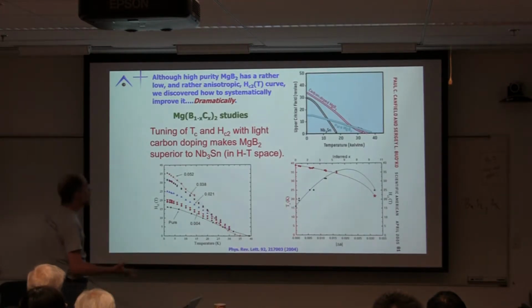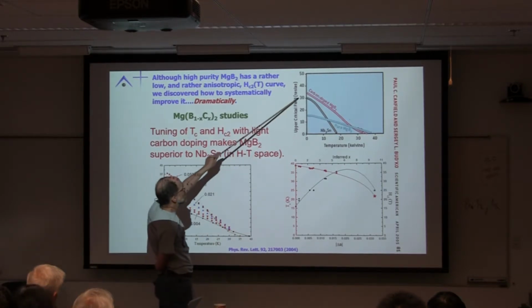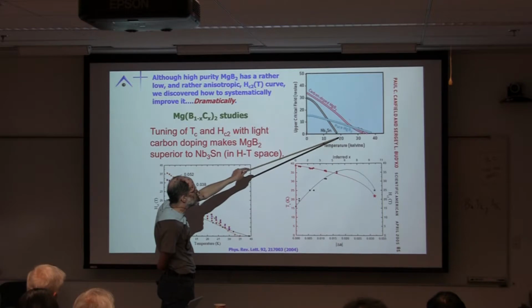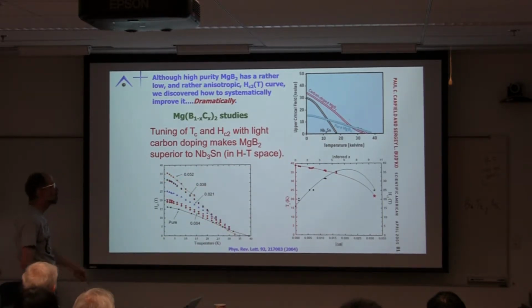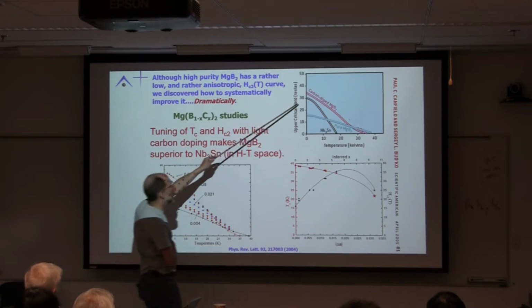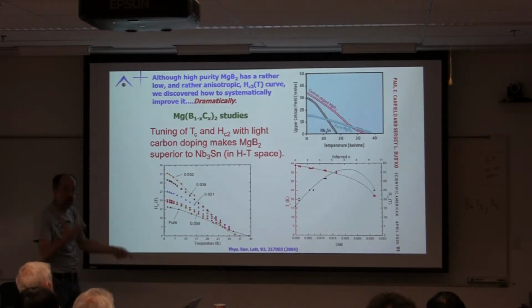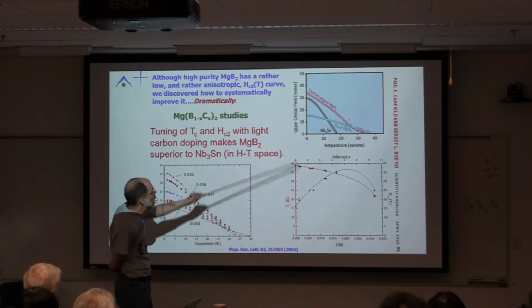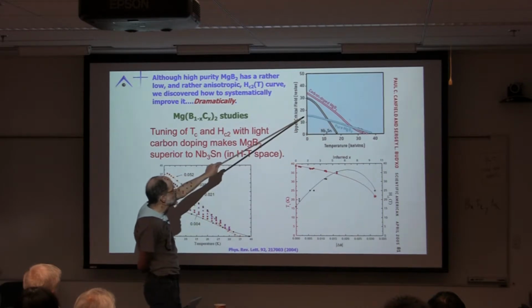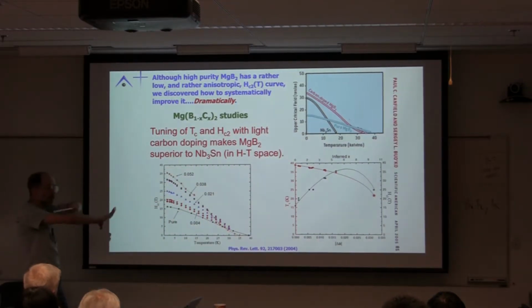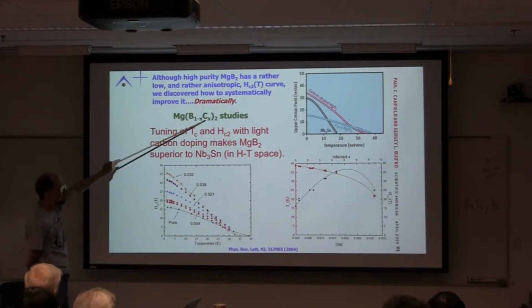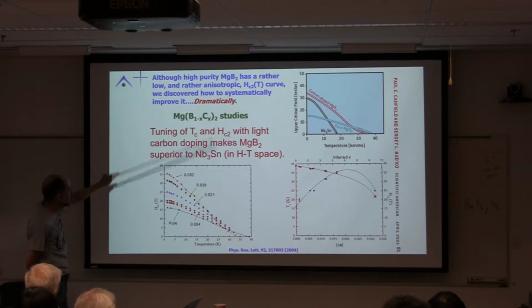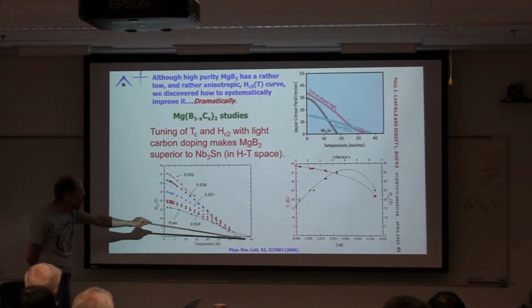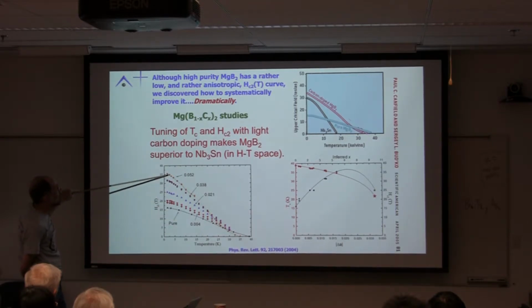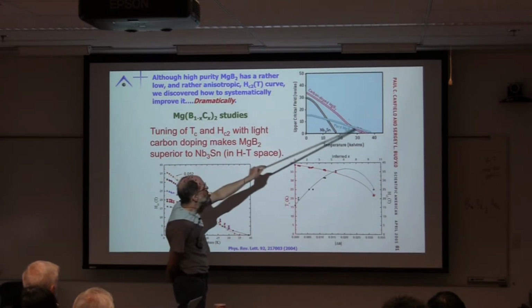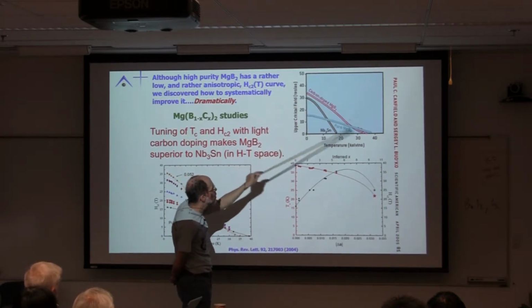Okay? What can we learn about superconductivity in this material? And we can put it in context. Here's niobium-3 tin. This is a highly optimized superconductor. There have been decades, and David Larbalestier and co-workers have grunted and sweated to get the last iotas out of the Hc2 here so it could be a good practical magnet material, okay? Now, pure MgB2, it has a higher TC, but the Hc2 is a little disappointing. On the other hand, since you have graphitic layers of boron, it's not too much of a revelation that maybe you want to substitute in some carbon into these graphitic layers, and as you do so, you mildly suppress TC from 40 to about 35, but Hc2 marches up. So in bulk, carbon-doped MgB2, you can supersede the Hc2 of niobium-3 tin over the whole temperature range.